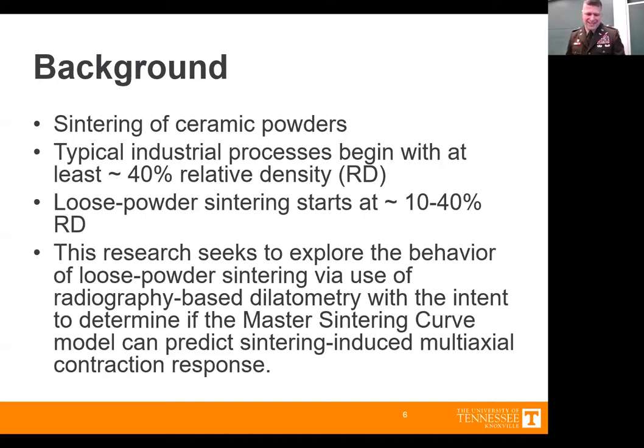Most industrial processes do something to the green body before they heat treat it that results in approximately 40 to 50% theoretical density of the green body. And then during sintering, it goes anywhere from 60% theoretical density up to 100% complete theoretical density. This work specifically was looking at much lower density ceramic objects. So my work was focused on loose powder sintering, i.e. I literally just poured a ceramic powder into a crucible, scraped it level, and put it into a furnace and tried to see what effect sintering had on the object.